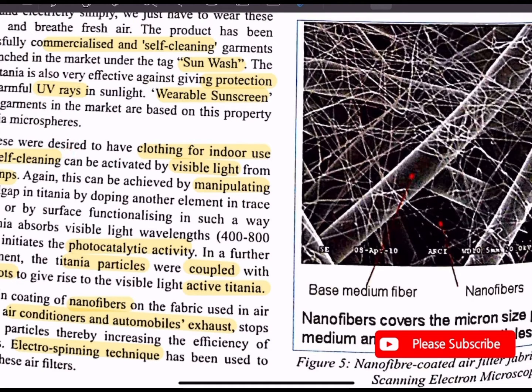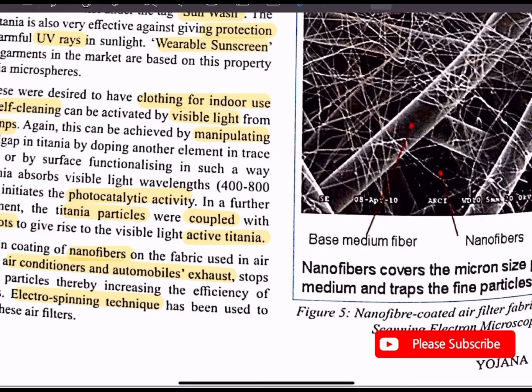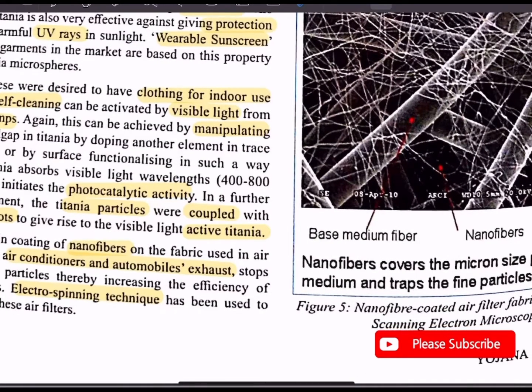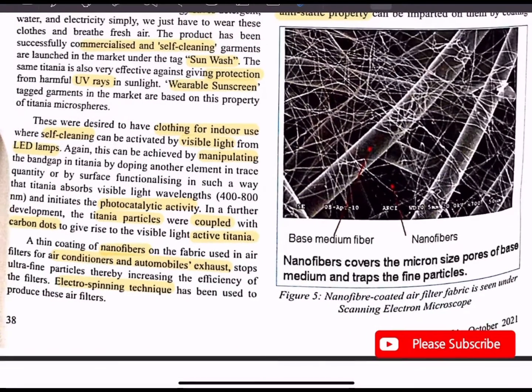These were desired to have clothing for indoor use where self-cleaning can be activated by visible light from LED lamps. Again, this can be achieved by manipulating the band gap in titania by doping another element in trace quantity or by surface functionalizing in such a way that titania absorbs visible light wavelength and initiates the photocatalytic activity. In a further development, the titania particles were coupled with carbon dots to give rise to the visible light active titania.